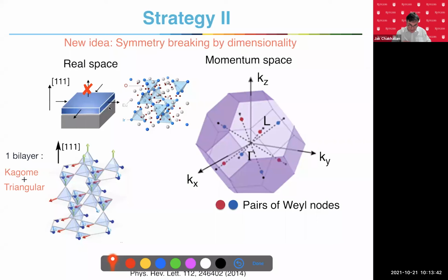They said, why bother with this pressure? Why wouldn't you grow a thin film? Just grow the thin film along this direction. And the surface, there is a special direction, right? There's a surface. So in this X and Y, it's the same, but the surface during the growth direction will break this symmetry for you. And so that was their proposal. And if you do that, this is the direction where you grow your film.